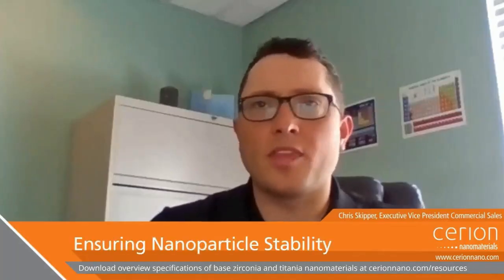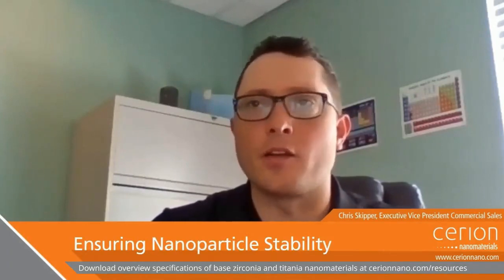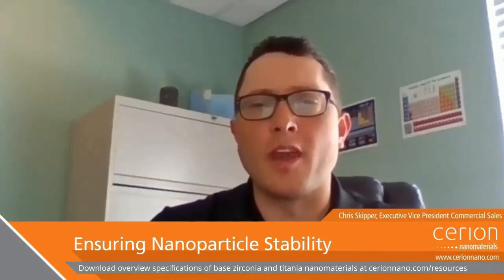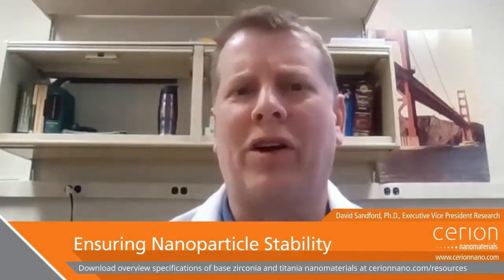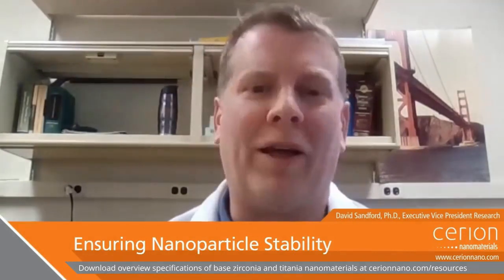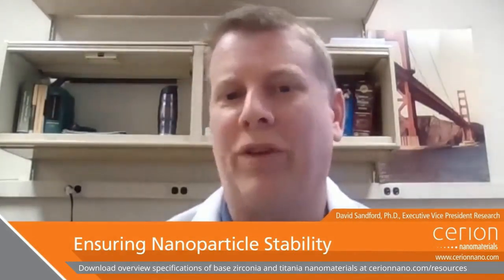So, when working with exotic solvent systems or a customer's proprietary solvent system under an NDA, how do you ensure the nanoparticles will remain monodispersed and stable in dispersion form? Well, typically with these systems, there needs to be some type of capping agent or stabilizing chemistry present in the dispersion to maintain the particle stability. Once we understand what solvent system our customer desires, we try to identify the optimal stabilizing chemistry to include in the dispersion. This not only maintains the integrity of the dispersion, but it's critical to our customers because it enables the highest particle-to-capping agent concentration possible, and thus the highest refractive index boost while preserving transparency and ensuring compatibility with their end-use system.